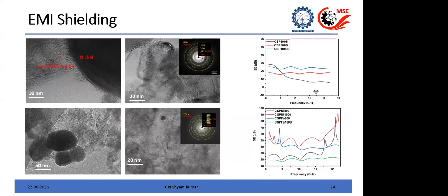EMI shielding properties. Now, in the graph here, the first three are heated to 1000 degrees Celsius without any catalyst, and the shielding efficiency is measured in the X band. Usually anything above 20 dB is considered a decent shielding material. So you can see the CSP 1000, this is CSP1000, is showing somewhere around 25 dB without anything. You just heat it.